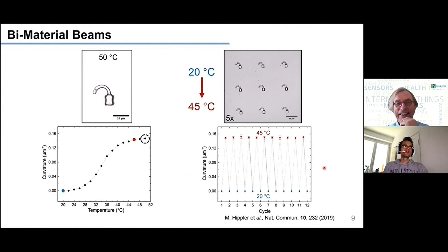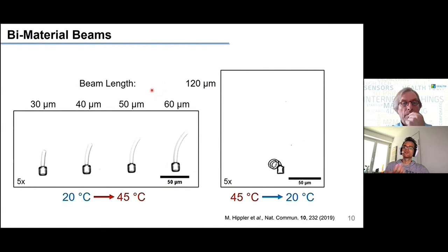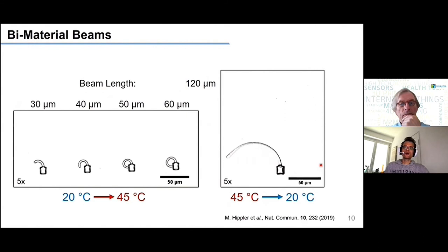I also want to show how geometrical aspects and design considerations impact behavior. As with bimetallic stripes, the aspect ratio has a huge influence. A movie shows different beam lengths from 30 to 60 microns, all showing nice bending — some even bending enough to touch the central pillar. For a beam 120 microns long, starting at 45 degrees Celsius in a completely curled-up state, cooling back down causes it to unfold and return to its initial shape — again demonstrating the reversible process.